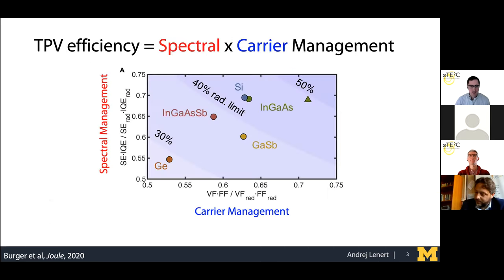So let me just give you some background as to where we stood before this work and how we got there. We published this in a review paper in Joule earlier this year, where we looked at the progression of TPV energy conversion and technology over the last three decades. And one of the things that came out of this analysis is framing the efficiency in terms of spectral management and carrier management. And so the efficiency is a product of those. And here I'm showing the progression along these axes of spectral and carrier management and how the different cells have been able to achieve different fractions of the radiative limit. So this is a thermodynamic limit that only considers radiative recombination as the carrier recombination mechanism.